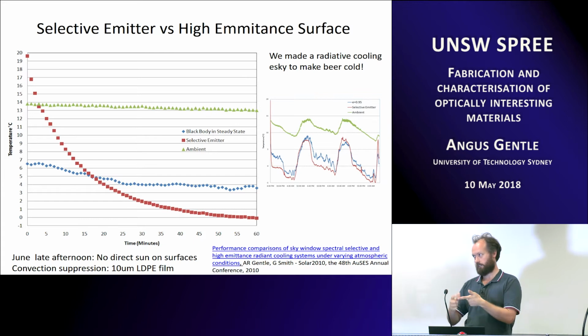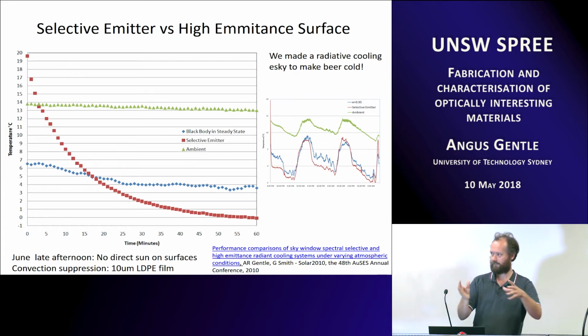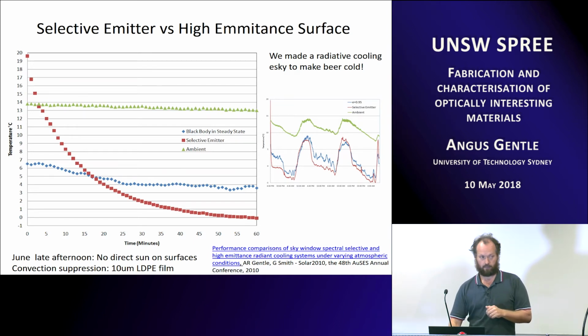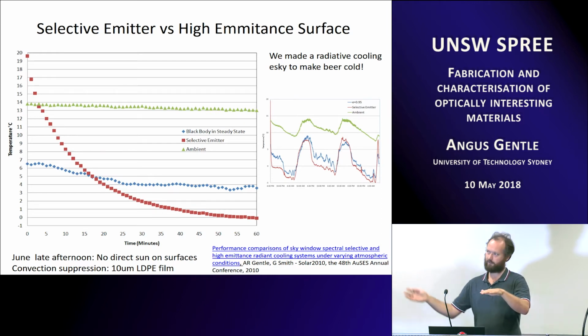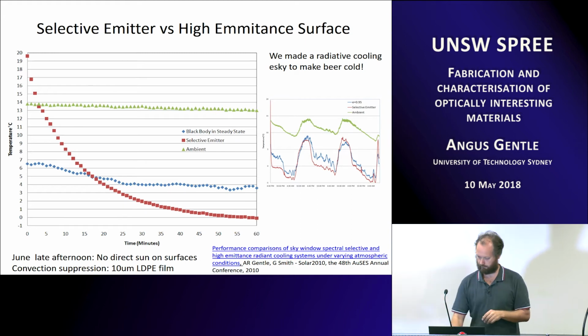These films, because they're silicon carbide and silicon oxide, are relatively dark. These were aimed at nighttime experiments, but we managed to get quite good cooling even in the late afternoon. That was in 2010 that we were doing that. That was a piece of glad wrap to stop air warming the sample back up. If you don't have the glad wrap there, you end up limited to about 7 or 8 degrees below ambient, because you've got a cold surface, the wind blows past it, and it just gets warmed up because of the amount of convection you get.